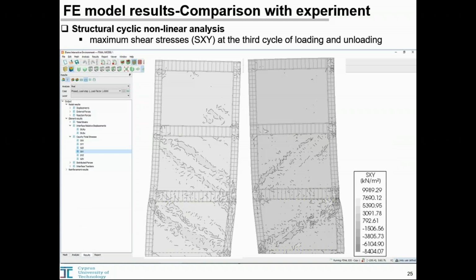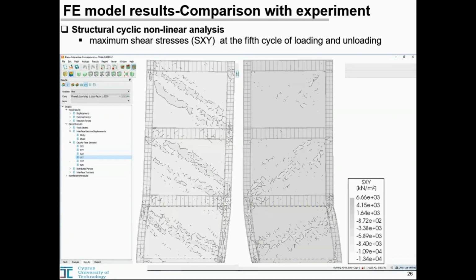In this slide, you can see the distribution of the shear stresses over the infill wall during the third cycle of loading. You can see clearly the diagonal strut develops within the infill at the first and second floor. In this figure, you can see also the shear stress distribution over the infill during the fifth cycle of loading. It is clear that the majority of the damage is concentrated on the first floor.